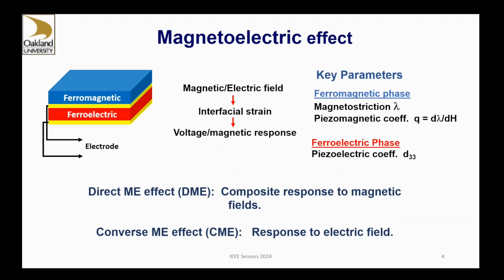So this can be utilized for magnetic field sensors, either DC or AC. The way it works is we have a bilayer of ferromagnet and a ferroelectric, and when I apply a magnetic field, there is magnetostriction in the ferromagnetic phase, which will be transferred to the ferroelectric phase, leading to a voltage response. And one could also argue that if I apply an electric field, you could have piezoelectric strain transferred to the ferromagnetic phase, which would manifest as a change in the magnetization or anisotropy field. The response of the composite to a magnetic field is called the direct magnetoelectric effect. That's the one we are interested in.